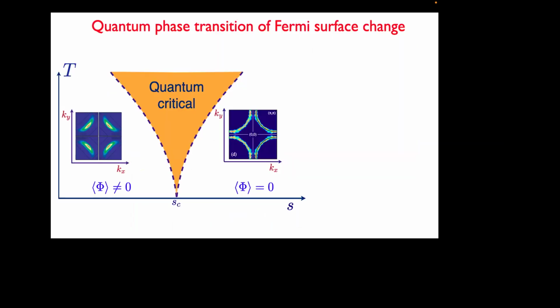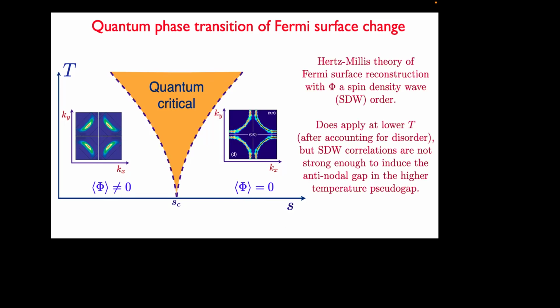So this is the kind of phase diagram you would draw. We have some parameter that you're varying, and then there's some scalar field, which when it condenses gives you the other kind of metallic state. This is something that Andy Millis has played a fundamental role in developing. If you take some spin density wave order parameter related to the antiferromagnetism, you can get some of the physics that's present in the strange metal. There's been a lot of progress on this recently after accounting for the disorder.